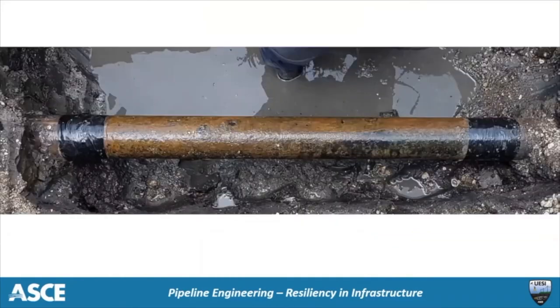As you can see, the film was installed as a sheet and it was very tightly wrapped, adhering somewhat to the pipe as Paul removed it. Here is the exposed pipe with the film removed. You can see the oxidation that is very visible. At this point, we will clean the pipe with a wire brush and water to determine the extent to which the corrosion has affected the pipe. You can also see the standing water in the bottom of the excavation, which required periodic pumping to allow us to conduct our examinations.